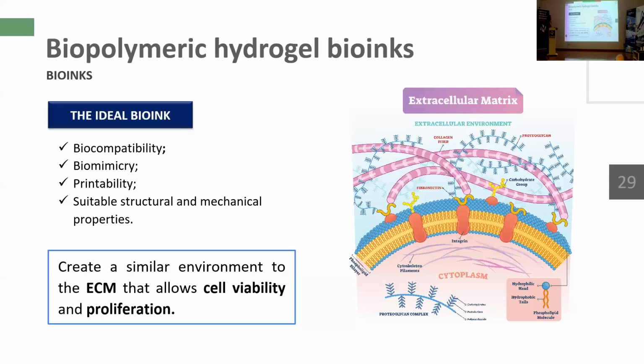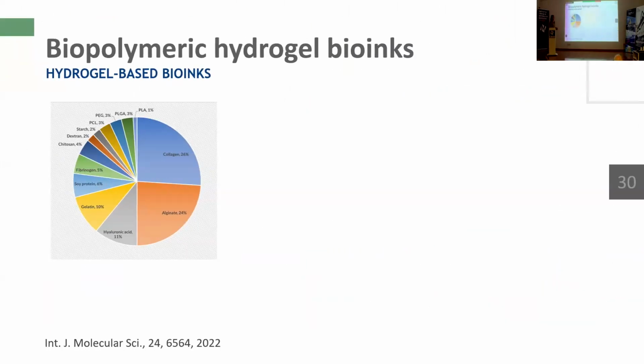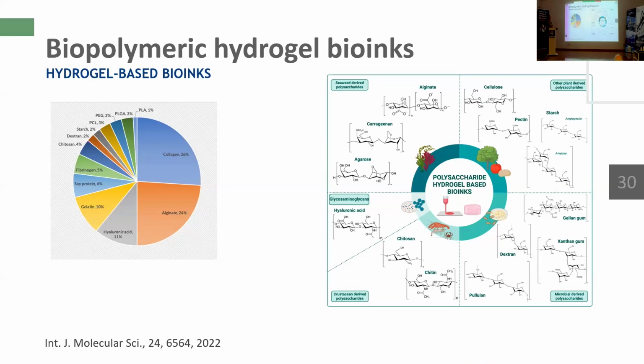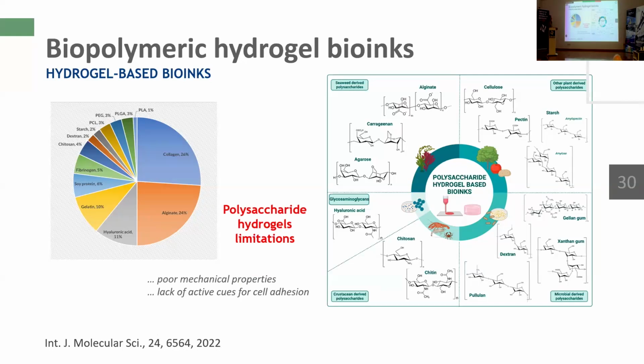There are different types of bioinks that we can use, but hydrogel stands out in this field, and particularly natural-based hydrogels. And in this realm, polysaccharide hydrogels have gained considerable attention, as we can see in this graphic, because we have a huge diversity of chemical structures that allow us to have different functional groups, to adjust the chemistry involved, and in particular because polysaccharides, most of them, can be cross-linked in mild conditions. That is important because we are talking about living cells. But not everything is perfect. Polysaccharide-based hydrogels present some limitation in terms of mechanical performance, and most of them lack active cues for cell adhesion.